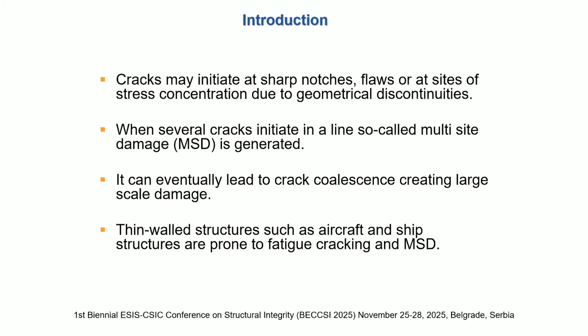So cracks may initiate at sharp notches, or at sites of stress concentration due to geometrical discontinuity. Several cracks initiate in a line, so-called multiple site damage is generated. It can eventually lead to crack coalescence, creating large-scale damage. Thin wall structures such as aircraft and ship structures are prone to fatigue cracking and multi-site damage or multiple cracks.